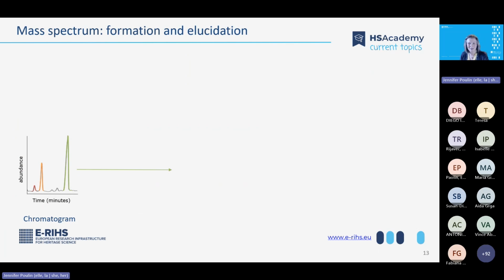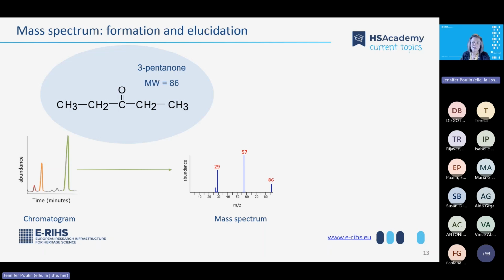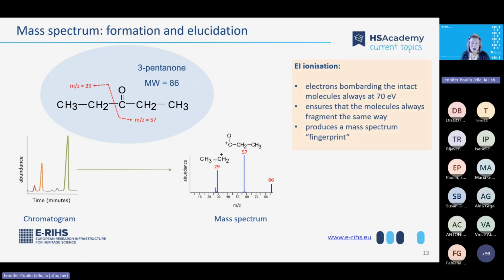So here's a little chromatogram. The green peak is made of a compound that fragments like this in the mass spectrometer. This compound is 3-pentanone, and it has a molecular mass of 86. When it's hit with an electron beam, it produces 3 main ion fragments. So 2 are formed from breaking the bonds between the carbonyl and the ethyl chain. And then we also see the molecular ion that occurs from the loss of a single electron from the entire molecule. 3-pentanone will always fragment like this during EI ionization, and this mass spectrum is its fingerprint.